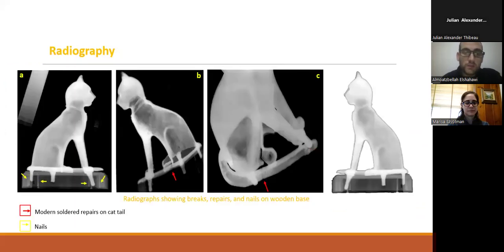Also, as for the radiography, the cat was x-rayed and found to be an accomplished casting with few defects. Radiographically opaque light areas, as we can see on the outer side of the cat, hinted at something nestled in the head. We decided it was time to remove the wooden base added by Reddy in 1892 and to take a closer look inside. What we saw on the interior was a completely different surface of varied topography with corrosion formed over a very long time. In the head, a dark mass, as we can see here, was tucked into the cavity, which also pointed to ancient modeling and casting.